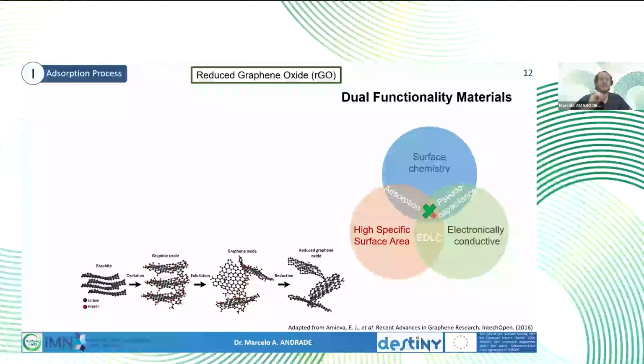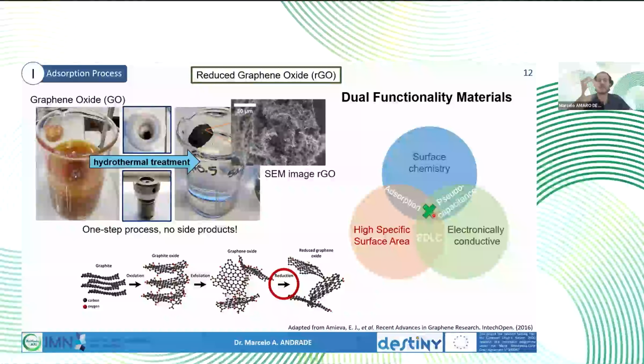So I initially thought of reduced graphene oxide, which is a derivative from graphite. It's basically graphite that was expanded, then exfoliated, oxidized, and finally reduced back into reduced graphene oxide. So it keeps some of the properties of graphene, such as the 2D structure. It recovers some conductivity and presents very high surface area. So that's an SEM image of reduced graphene oxide. You can see it's highly porous and it's floating in water, so very, very low density.